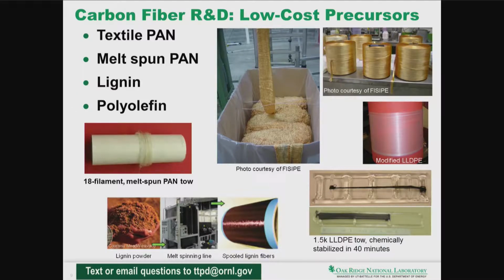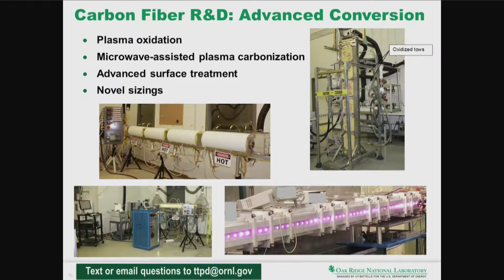So the efforts that they have in the area of low-cost precursors is moving from the typical PAN that is used, PAN is polyacrylonitrile, focusing on textile PAN or melt spun PAN and eliminating the solution-based processing, but also looking at alternate materials such as lignin and polyolefin. And then on the processing side, they've focused on the processing steps that are very energy and time intensive, and developed new, less energy intensive and much faster processing steps, such as plasma oxidation and microwave-assisted plasma carbonization.